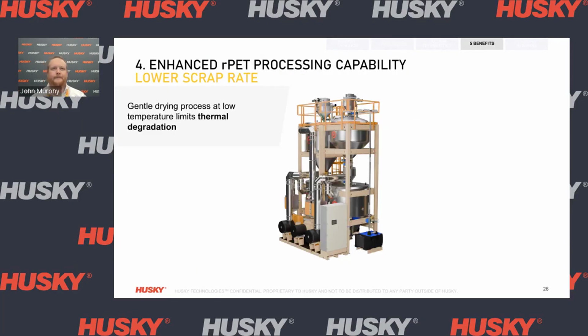Earlier in the presentation, I spoke about the challenges that come with processing rPET material. Now I would like to walk you through these challenges and how the vacuum technology can be used to address these challenges. One of the key benefits of the vacuum dryer is that resin is kept at a low temperature, below 160 degrees, for 75% of the drying process. This gentle drying process significantly reduces thermal stress on the resin and limits the potential for thermal degradation.